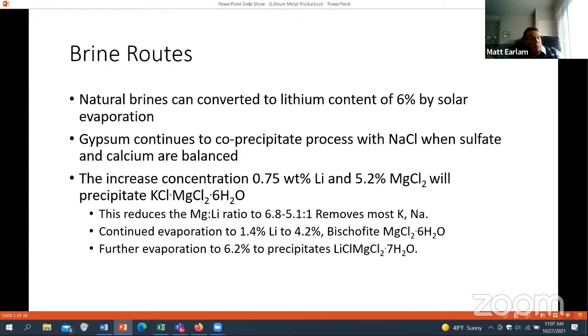So let's talk about the brine route, because this is where most of the stuff is actually converted at this point. So the natural brines can be concentrated by solar evaporation to about 6% lithium, as we use lithium as lithium chloride as a basis, just because that's the basis that they use to look at. So as the brine evaporates, the sodium chloride and calcium sulfate drop out of solution. And then you end up with a concentration that's a lithium magnesium chloride double salt, similar to carnallite, which is shown here. The potassium will also drop out as carnallite.